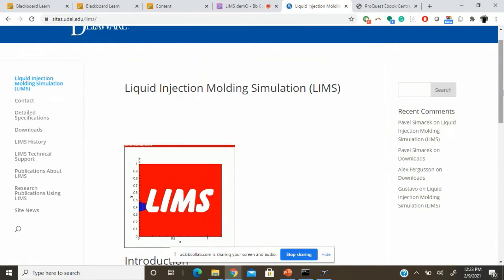Similarly, our main purpose of using LIMS is, before taking up an experiment to impregnate a complex model, such as parts of a car or so on, or even for a bridge building competition, we usually try to model, let's say, a square beam or I-beam using LIMS and further impregnate the entire beam with the resin, so that we can optimize where the location of the inlet ports of the resin must be, so that we get no dry spots or no voids along the entire mold itself.